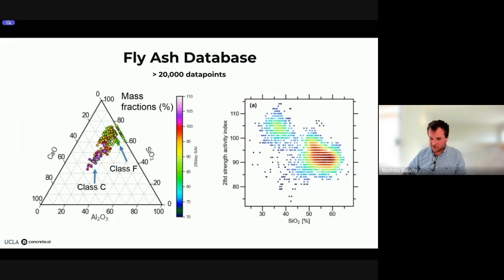So fly ash is typically like a calcium aluminosilicate material. So depending on the fraction of calcium, silica, and alumina that you have in fly ash, it's going to have different types of reactivity. It's going to impact the strength of concrete in different ways. So again, we need to explicitly take this into account when we predict the performance of concrete, because fly ash is very heterogeneous. The properties of fly ash can change a lot from one plant to another, and it can change over time. So we need that level of detail to really be able to make some predictions.